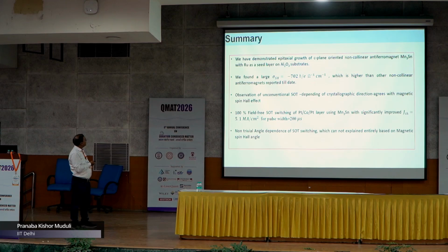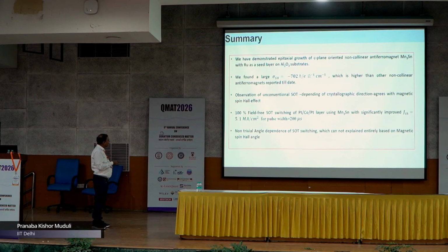So this is the summary: we have grown very high quality epitaxial Mn3Sn and we have measured a large spin Hall effect, spin Hall conductivity. We observe this unconventional SOT which agrees with the magnetic spin Hall effect, and then we are able to get switching with better performance. There is also a little bit of angular dependence of switching that I didn't discuss, which is related to the magnetic spin Hall effect, but is a little bit complex, so I skipped that in this talk.